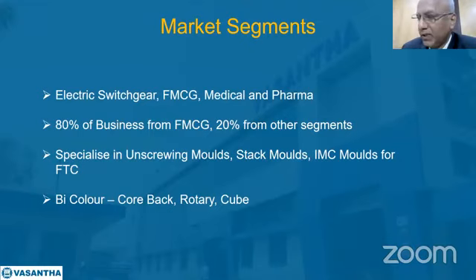And at Vasantha, we also use a lot of additional infrastructure to test these molds, like rotary tables. When you say the second category is rotary, to run a rotary mold, you need a rotary table mounted onto the injection molding machine. And to do all this bicolor, tricolor molding, you also need to have a secondary injection unit or tri-shell injection unit, means you need to have additional injection units. Sometimes, in fact, we have done some molds like that. The second color itself gets injected at two places, though the injection is taking place totally at three places, means the primary color and the second color can get injected at two places, but it's called tri-injection, but two colors.